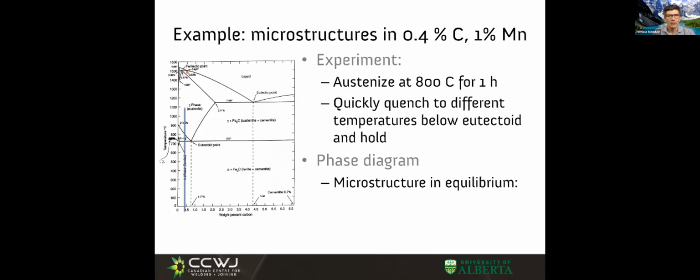We also saw a number of other things: there's only so much carbon we can put in iron, and if it is in the atomic arrangement of austenite, then we can put up to 2.1% carbon in the austenite. That's a lot. I say a lot because 0.4% is already a lot of carbon from the point of view of welding. 2%, imagine that, is 5 times that.